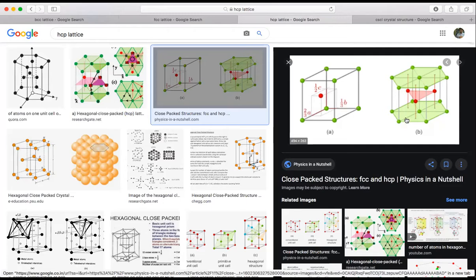So then the stacking would have been ABC, ABC, ABC. This ABC stacking is just the 111 planes of the FCC lattice. So there's a very close connection between the FCC lattice and HCP lattice. In HCP lattice, you have AB stacking of atoms perpendicular to the C axis. In FCC lattice, you have ABC stacking of the atoms perpendicular to the 111 direction.